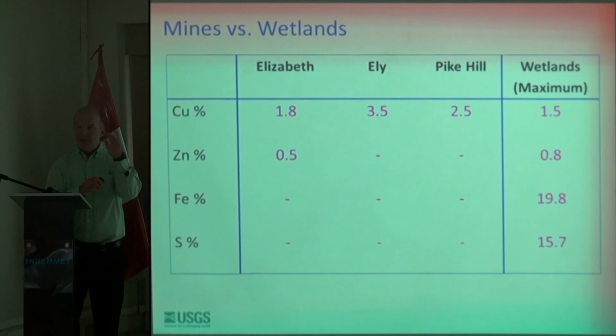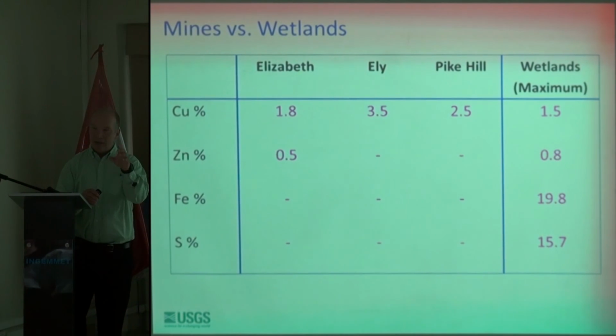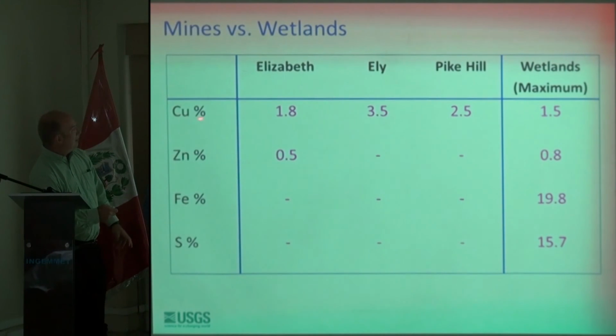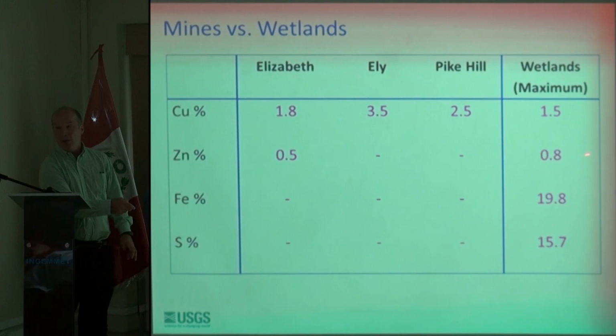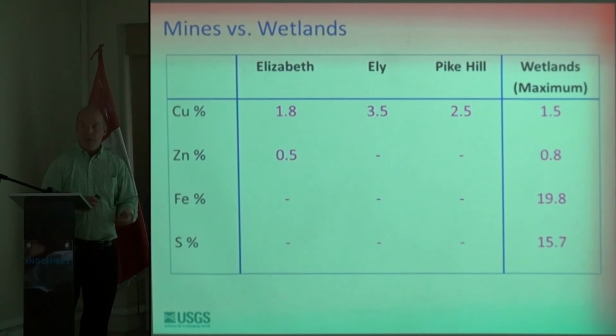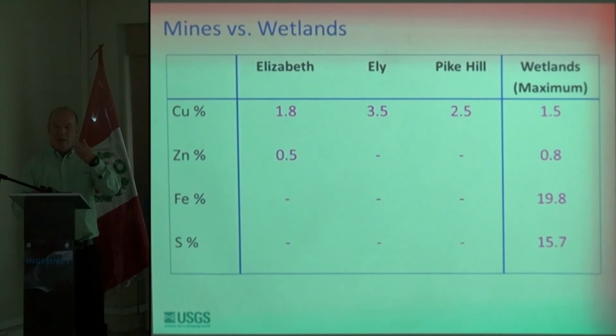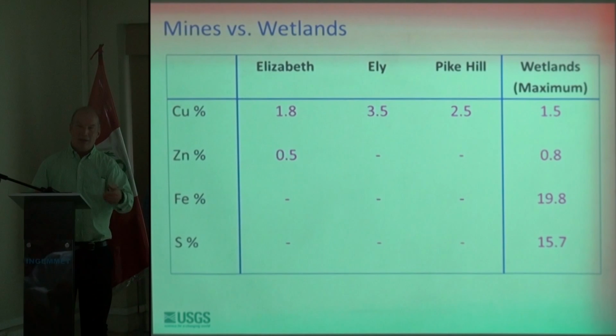When you look at those individual samples in the wetlands of these sulfide minerals that are forming today, you can see that the copper grades that we're seeing forming in the wetlands are basically ore grade compositions. The amount of zinc is quite high, ore grades as well. Iron's high, which we don't have information on in the ores, and then the sulfur's quite high as well. So basically what we're doing here is taking mine waste, mobilizing it, and reforming an ore deposit there in the wetlands.